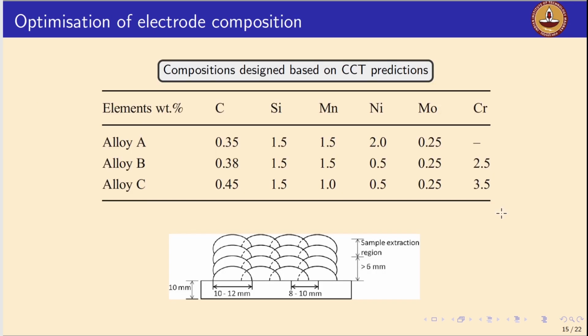From the hot cracking susceptibility, we can identify the possible chemistries subsequent to the hot cracking test. I'm showing you three chemistries which are optimized in this case, based on the CCT and subsequently the hot cracking test. We identify these three chemistries, and then we actually make the weld deposits using them. We take samples from these multipass welds for Gleeble simulations to understand the phase transformations, and subject these samples to various dilatometry analysis. I'm just going to show you a case study for these chemistries.